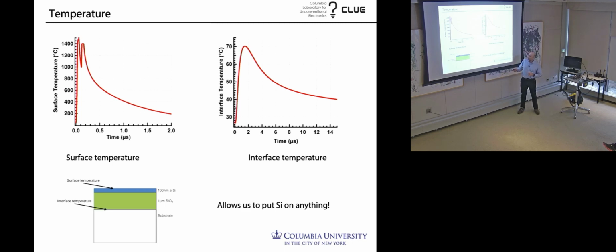But anyway, when you hit it with the pulse, it gets hot, it melts. When it melts, it sucks in the heat of fusion, kind of like an ice cube melting in your water. That cools the silicon slightly. It then solidifies, it pushes that heat of fusion back out, and it gets hot again, and then it relaxes. All that happens in 0.1, 0.2 microseconds. So we hit a very high temperature, but the heat diffusing from the top to the bottom takes about 2 microseconds. And by the time that's happened, we've spread all of that energy across a thermal mass that's about 10 times that of the silicon we melted on top. So it's possible for us to make relatively high performance transistors without really damaging the substrate.